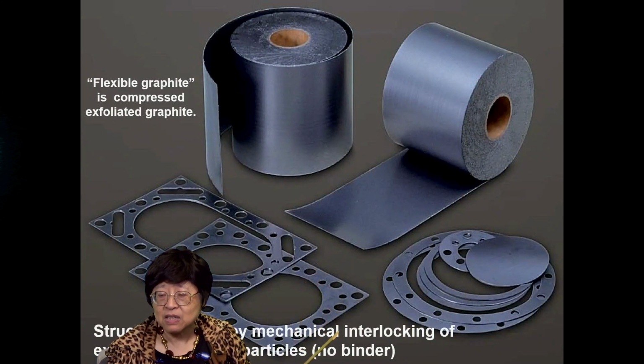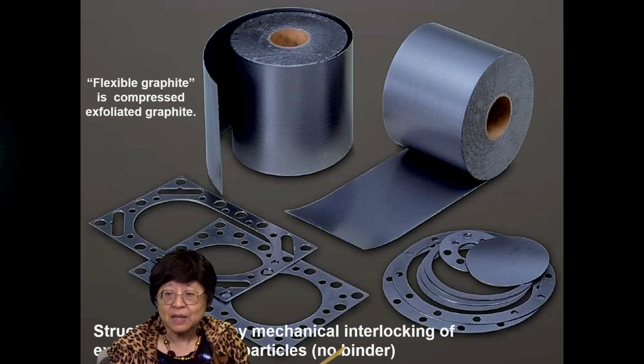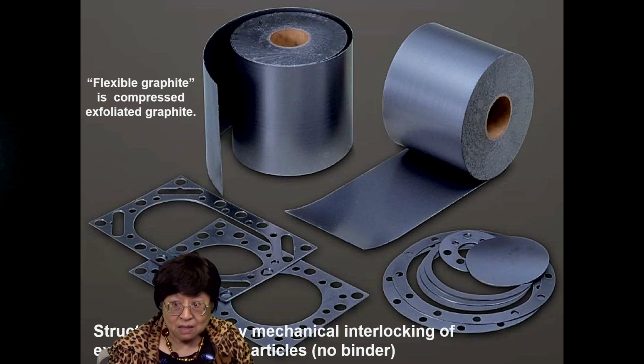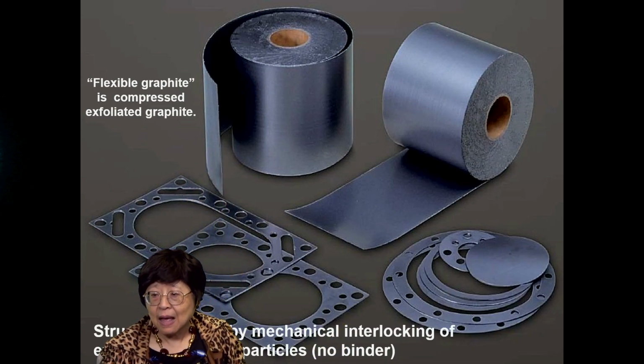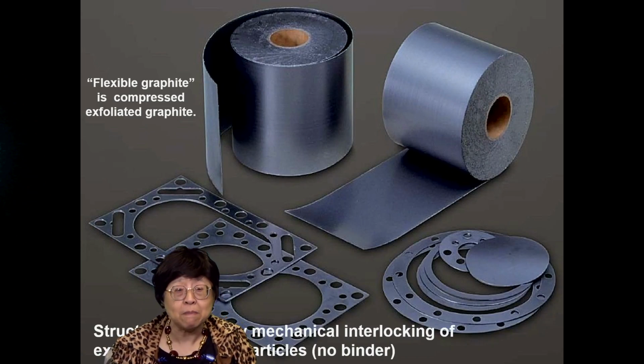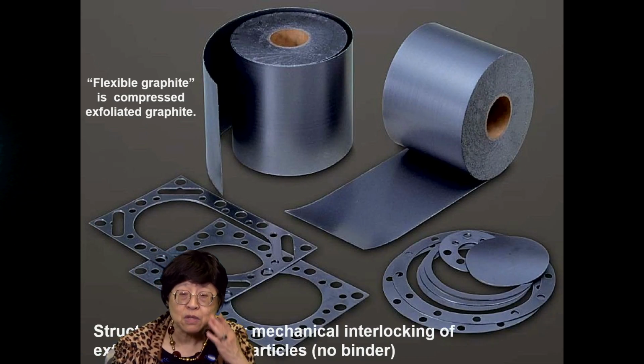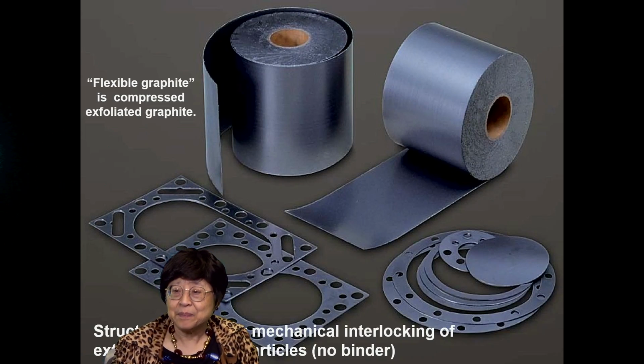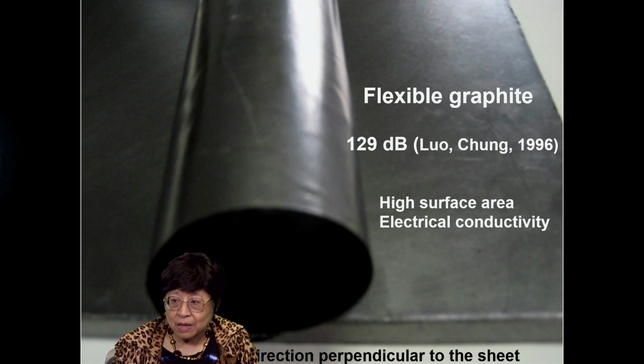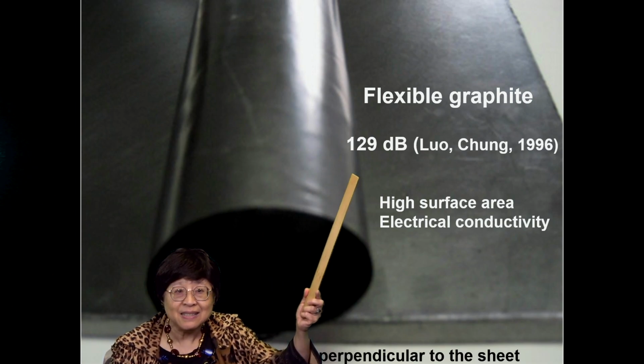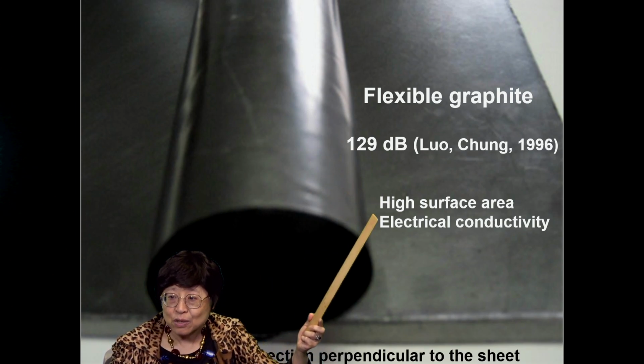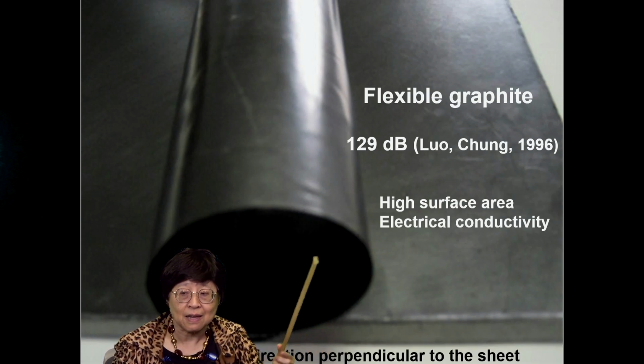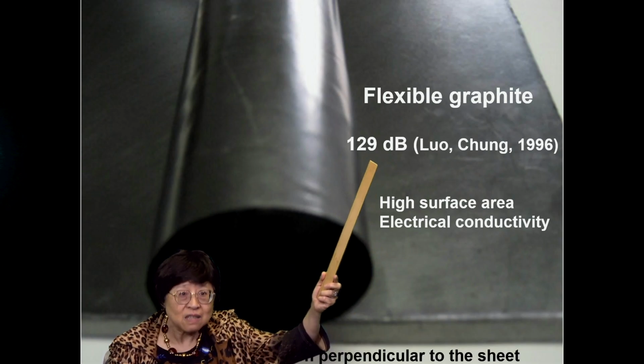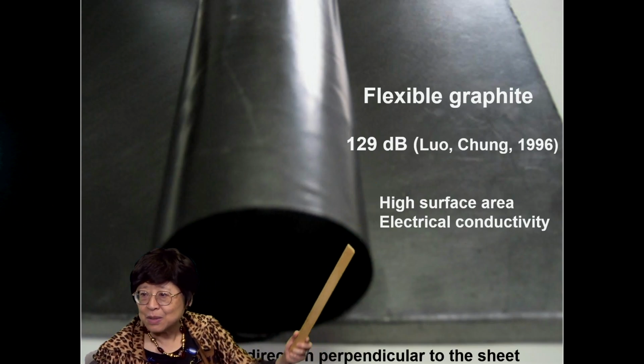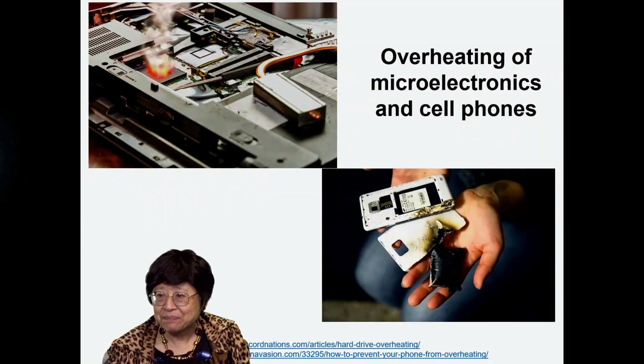And you can have a pile of these worms and then compress them. It forms a sheet called flexible graphite. And there's no binder involved, just the mechanical interlocking between the worms due to the fact that each worm has a cellular structure. And by using this material, we attained 129 dB, high surface area as well as electrical conductivity. And this is today still the record. This was back in 1996.